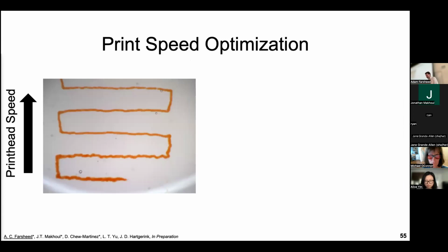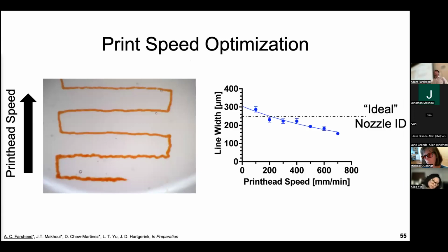So then we went ahead and did some print speed optimization like we did in the first aim again. We're basically printing a continuous line by moving faster and faster, and we can again measure the line width. And what I want to call your attention to is this ideal nozzle diameter of 250 microns. In our old system, we couldn't get anywhere close to that. But in this new system, we're actually able to get to that ideal nozzle inner diameter for our line width and even underneath that. And I know that's a little bit weird, but basically we're able to get resolutions that we were unable to achieve in the past.